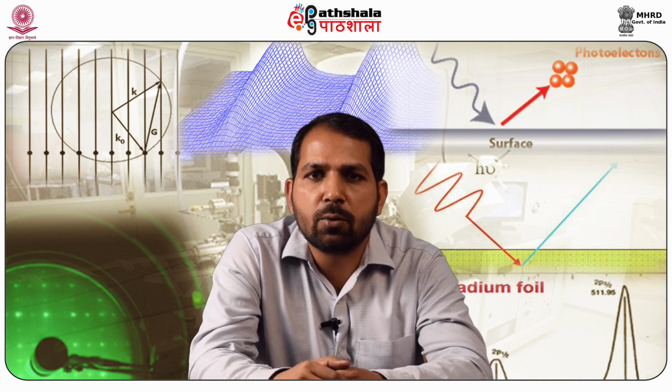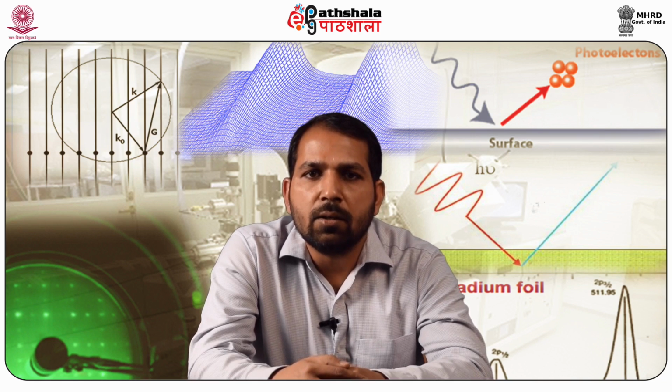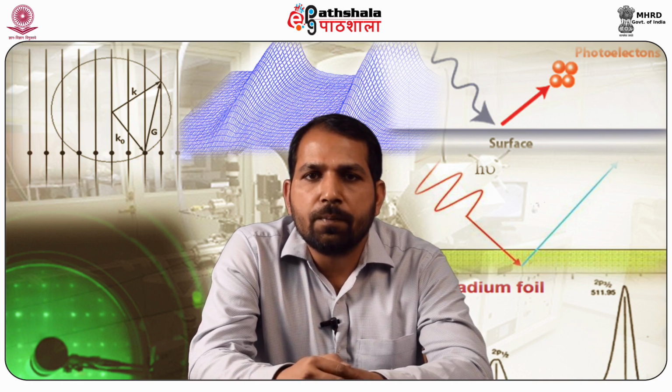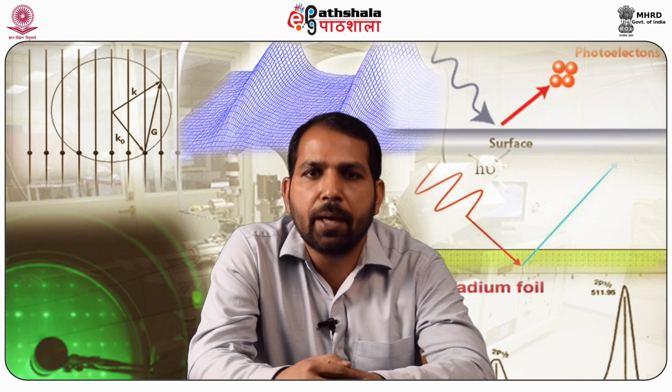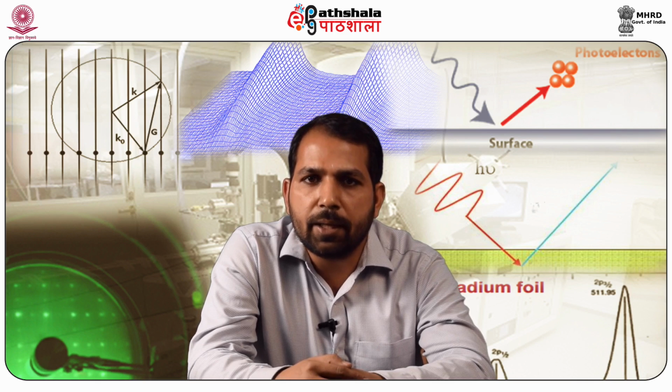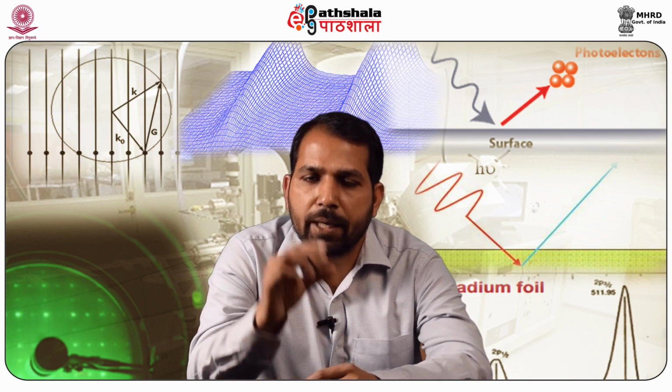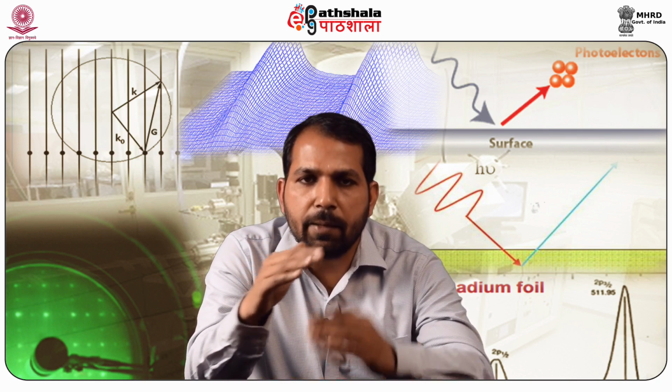STM experiments with atomic resolution are always performed with very short tip sample distance. Direct measurements have shown that the normal tip sample distance in STMs is 1 to 4 angstrom before a mechanical contact. The experiments were simultaneous measurement of the force gradient and the tunneling conductance in an STM. By integrating the force gradient, the point of mechanical contact is determined. The tunneling conductance as a function of the tip sample distance with respect to the point of mechanical contact is directly measured.